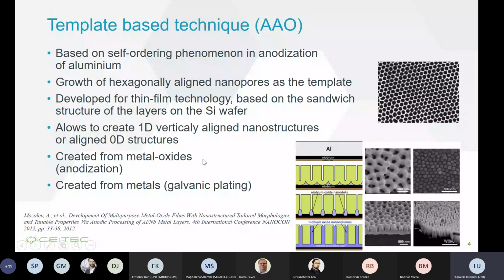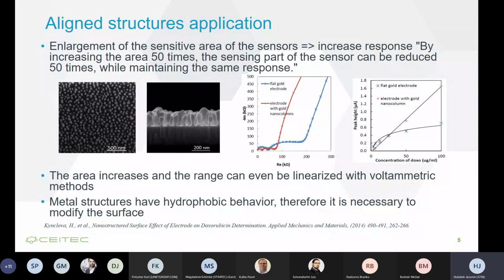Using this method we can create metal oxide if the refractory metal is deposited on the bottom, and we can use galvanic plating to fill the nanopores, so we can obtain metallic nanostructures. The first application which we did was enlargement of the sensitive area. It was motivated by miniaturization with this statement: by increasing the area 50 times, the sensing part of the sensor can be reduced 50 times while maintaining the same response.